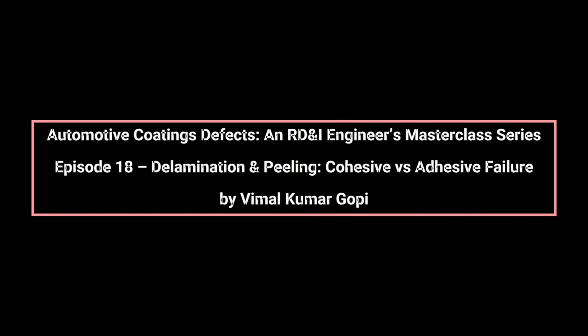Delamination and peeling are among the most expensive and reputation-damaging failures in automotive coatings because they represent a complete loss of system integrity. Unlike appearance defects, these failures are structural, meaning the coating system can no longer protect the substrate or survive service conditions. From an OEM RD&I perspective, delamination is never treated as a paint problem alone. It is a failure of interfacial physics, stress management, and long-term durability design.